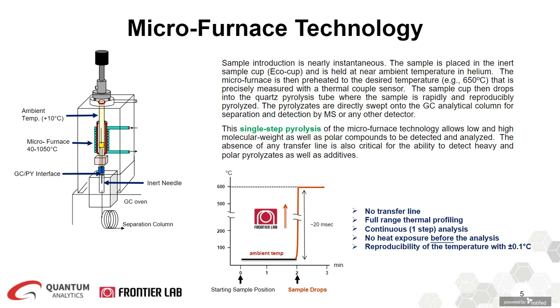The microfurnace also allows a full-range evolved gas analysis, EGA, to obtain a thermal profile of an unknown sample for any light compounds, additives, volatiles, oligomers, polar, heavy, and polymeric compounds. These EGA experiments can be performed from 40°C to more than 1000°C and correlate results to the well-established TGA, thermal gravimetric analysis, techniques throughout the entire temperature range of the experiment. The microfurnace technology also guarantees reproducibility and accuracy of the temperature within plus or minus 0.1 degrees Celsius. All the surfaces are quartz or temperature stable deactivated.